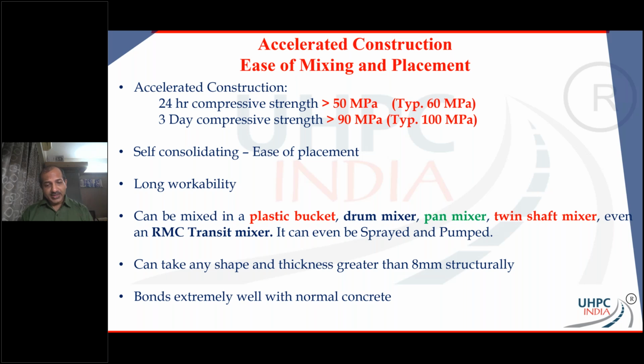Not even that. Let's say if I give you a dry mix of UHPC, you can directly put it into a transit mixer and mix it there. A transit mixer is just your regular concrete readymix transit truck. And you can pour your UHPC as you want it. Believe it or not, UHPC can be nicely sprayed and even pumped. Very recently, just about a couple of days back, we pumped, for the first time in the country, UHPC almost 13 stories high, and we're pretty happy about it.